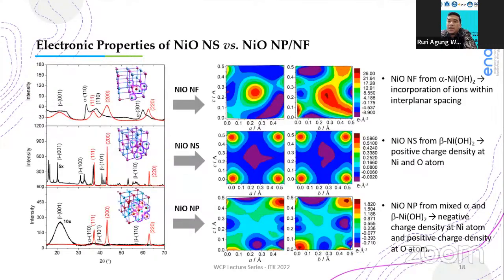So here we compare all three nanostructures, and it is obvious that the electronic nature is different. Nanoflakes, for example, which is predominantly from alpha nickel hydroxide, has charge distributions within the unit cell, which might be due to ionic impurities in the interlayer spacing. Nanostars, which is formed from beta nickel hydroxide, has positive charge distributions at both nickel and oxygen atoms. Meanwhile, the nanoparticles, which is obtained from the mixed alpha and beta nickel hydroxide, has mixed character of charge distributions in both nanostars and nanoflakes.